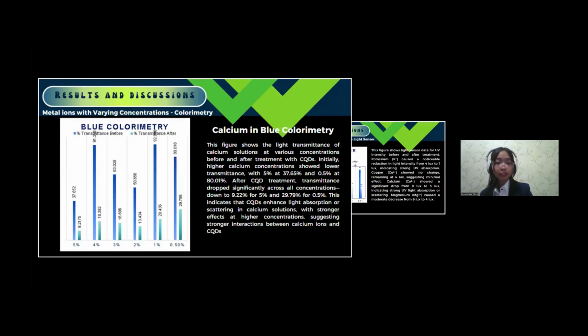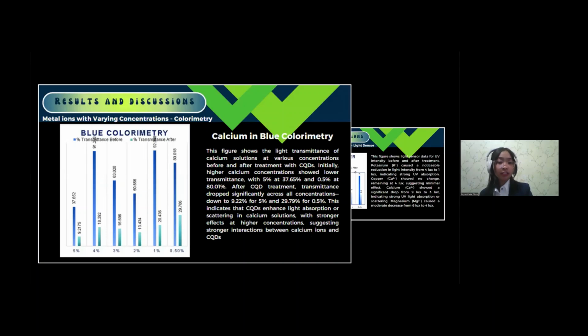We now move on to the data showing the varying concentration, following the same process as before with the NeuLog Logger sensors. This shows how calcium solutions at different strengths let light through before and after adding CQDs. Before treatment, higher calcium levels block more light, about 37.65% transmittance at 5% calcium and 80% at 0.5%.